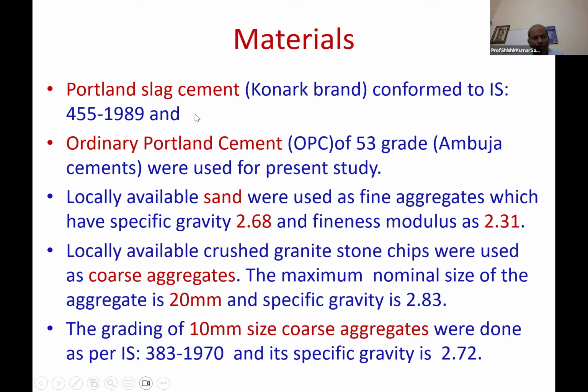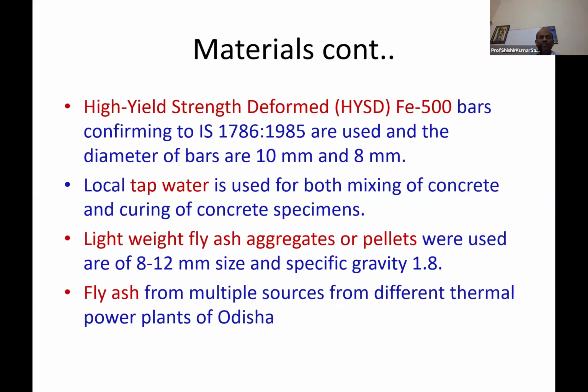So we have done both slag cement and OPC, with locally available sand as fine aggregate with specific gravity 2.68, and locally available crushed granite stone chips as coarse aggregate, maximum nominal size 20 mm. The grading of 10 mm coarse aggregates was also used. In the case of tiles, we have used 10 mm size aggregate. For the rest, normal concrete, we have used 20 mm size aggregate. High yield strength deformed bars, Fe 500, conforming to IS 1786, and the diameters of the bars are 10 mm and 8 mm. Local tap water. Lightweight fly ash aggregates or pellets are of 8 to 12 millimeter size and